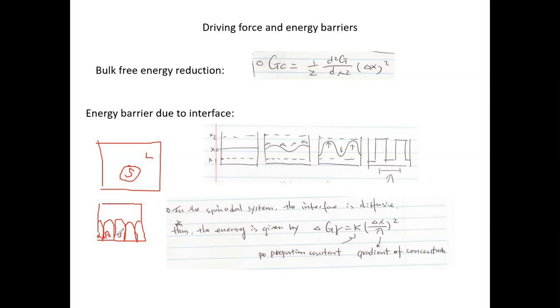So although you still have to worry about the difference of the composition, the crystal structure already gives you a huge increase of the mismatch strain energy that's going to cost you a lot for the interface. So those are the typical understanding of the driving force and the barrier, especially the barrier due to the interface.